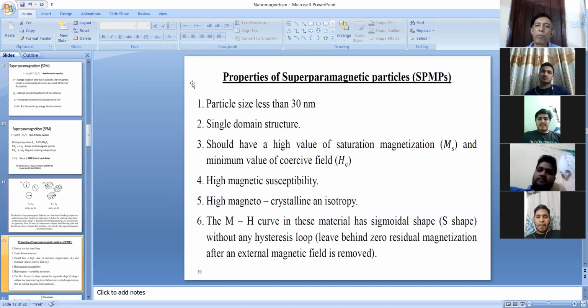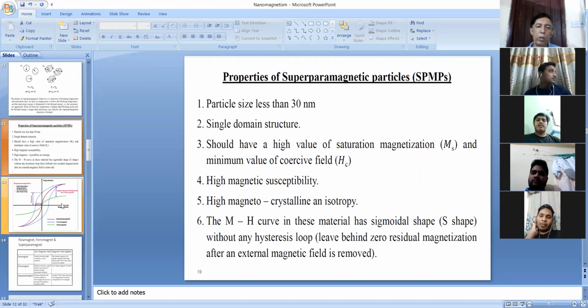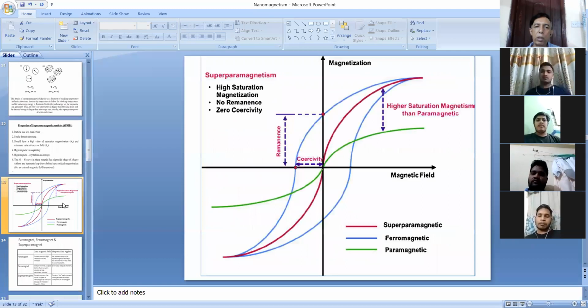So the properties of superparamagnetic materials: their particle size will be less than 30 nanometers. It will be a single domain structure. It has a high value of saturation magnetization, high magnetic susceptibility, high magnetocrystalline anisotropy, and the hysteresis loop, the magnetization or M-H curve. This is the hysteresis loop. We'll explain this tomorrow. This is the hysteresis loop of superparamagnetic substances.